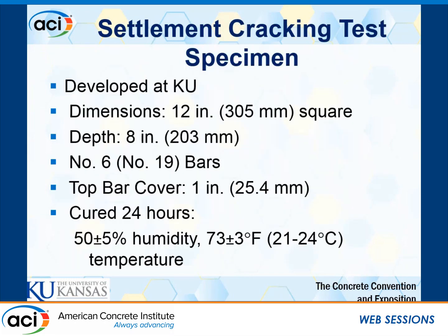So to evaluate settlement cracking, we developed a qualitative way of looking at different crack reduction technologies. We use a 12-inch by 12-inch square by 8 inches deep specimen. We cast concrete over a number 6 reinforcing bar. For what we're looking at in this particular test program, we used 1 inch of bar cover for the settlement cracking specimens as well as our reference corrosion test specimens. We hold a pretty strict curing and finishing regime with these to make sure that that variable is not controlling anything from one set to another.